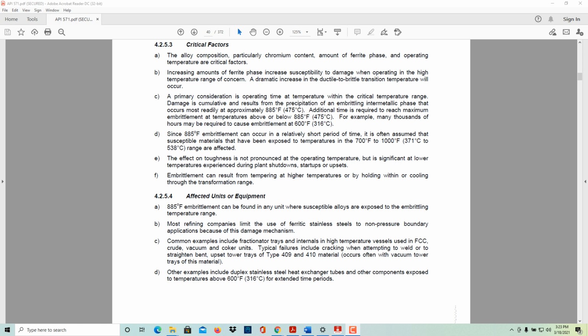The effect on toughness is not pronounced at the operating temperature, but significant at lower temperatures experienced during plant shutdowns, startups, or upsets. Embrittlement can result from tempering at higher temperatures or by holding within or cooling through the transformation range.